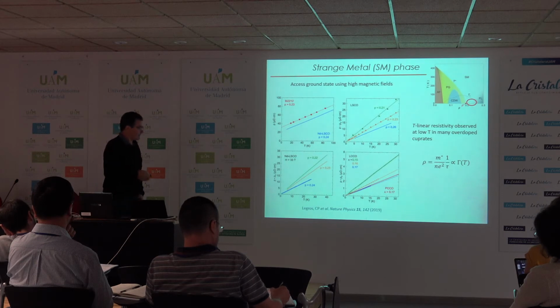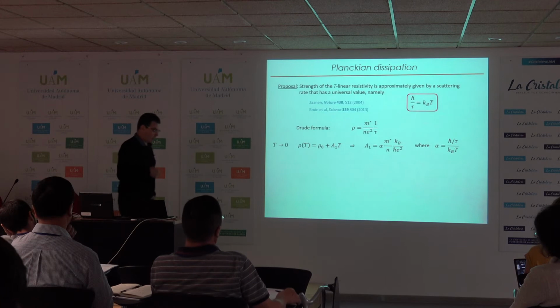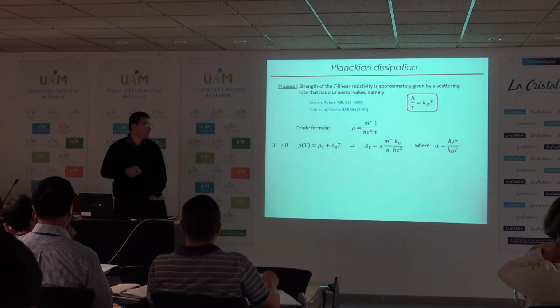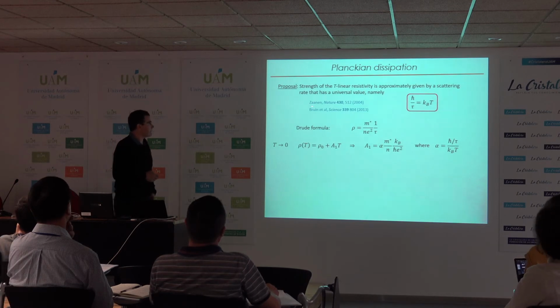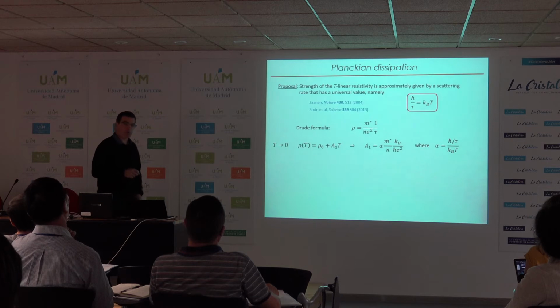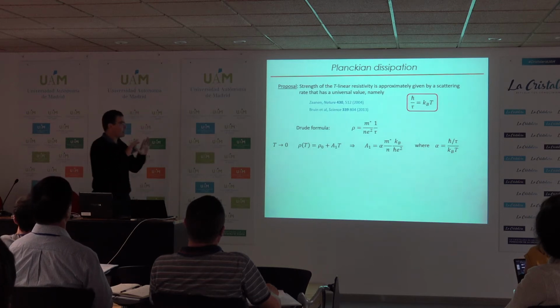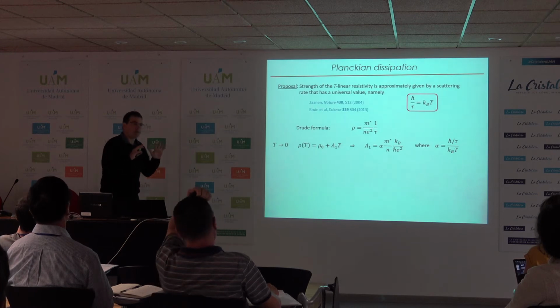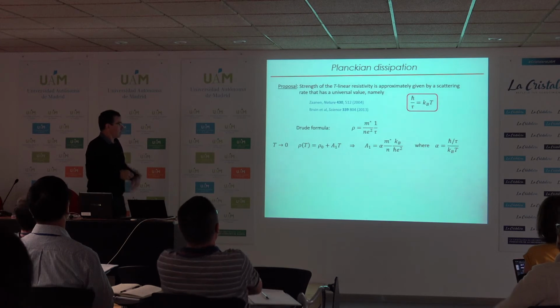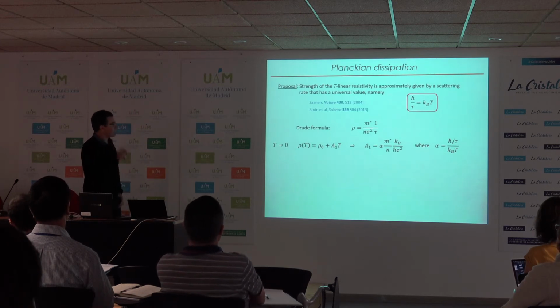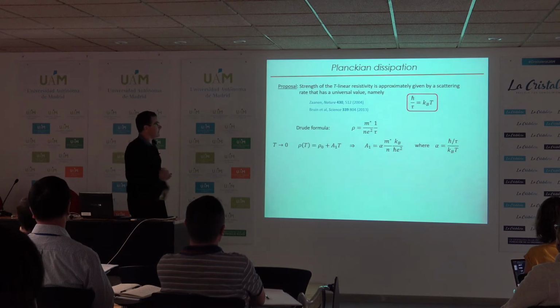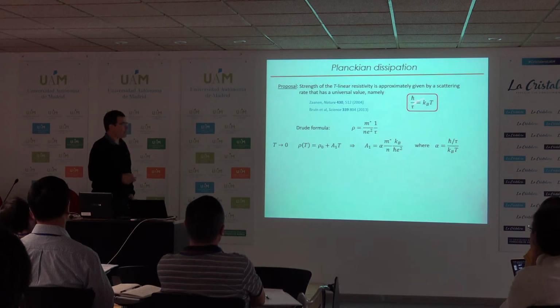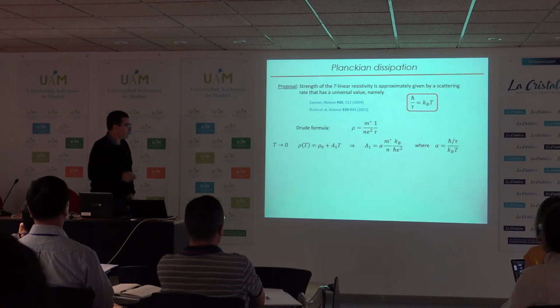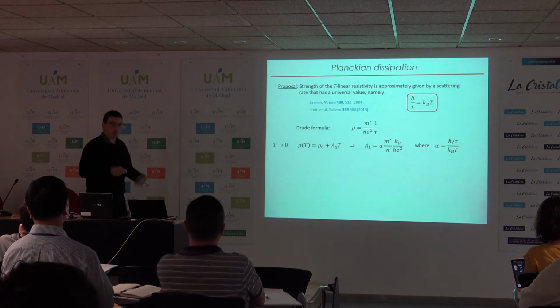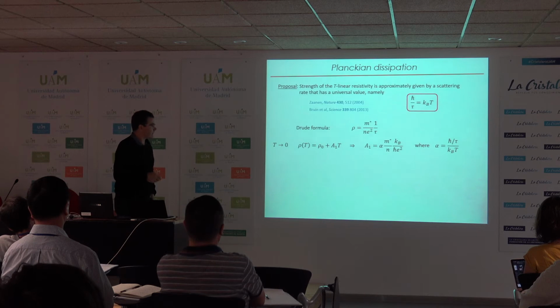And what we have done in this paper is that we have followed a current idea of what we call Planckian dissipation that has been introduced by Jan Zaanen back in 2004. And there is a very beautiful experimental paper by the group of Andy Mackenzie where they have compiled a lot of results on different strongly correlated electron systems, proposing that the strength of the T-linear resistivity is given by a scattering rate that has a universal value, namely a scattering rate proportional to kBT over ħ. And if you assume that, and you plug that in the Drude formula, and since we are close to T equals 0, we assume that we can use this formula to